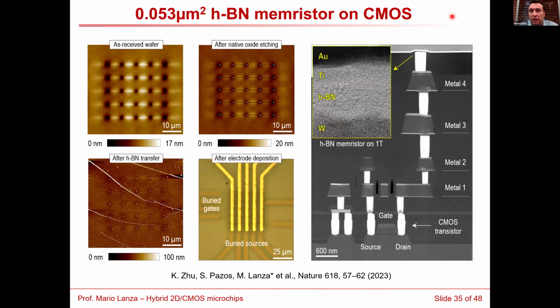Some tricks about the fabrication. The wafer, as we extracted it from the factory, comes with native oxide. It needs to be removed to expose the vias before transferring the boron nitride and patterning the top electrodes. Okay, and then what you have is the transistor that is connected through all the metal layers to the surface. And here on the surface, we transfer the boron nitride, and then we have the boron nitride and the top electrode. Then we have a device that now is 0.053 micrometers square with structure gold, titanium, hBN, tungsten, which is the material of the via.